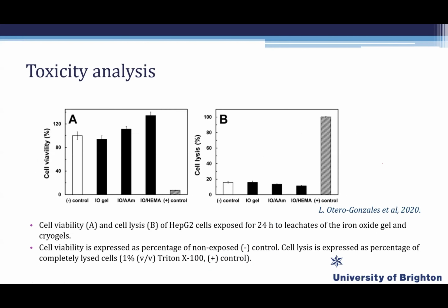Of course, if you're using these materials as filters for water, and that is what they were designed for, you need to consider the toxicity of these materials. And we have done the analysis of toxicity using cells. And as a result, they show cell viability and cell lysis of HepG2 cells. Exposure to these materials for 24 hours doesn't change compared to the control.